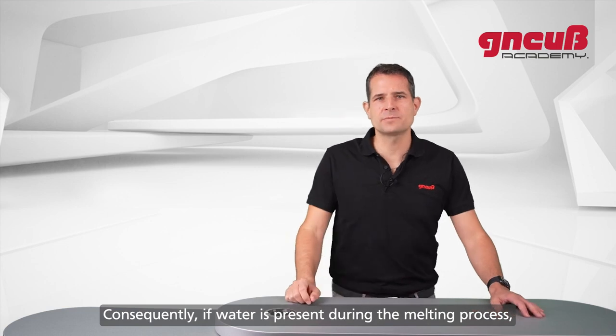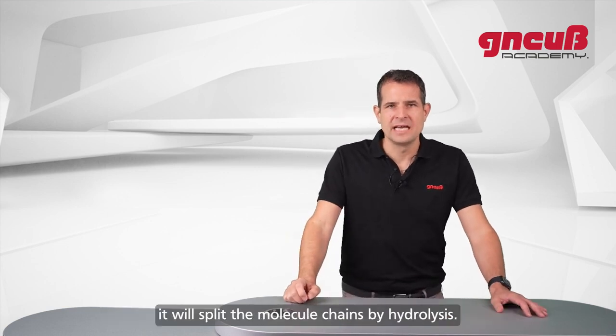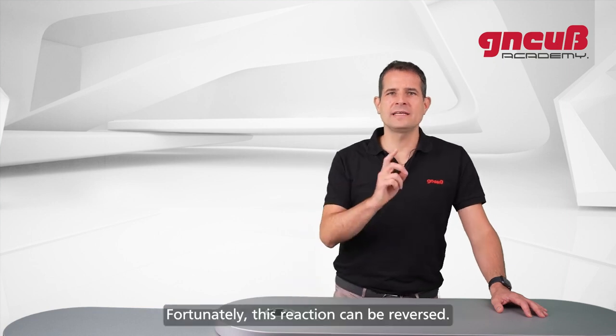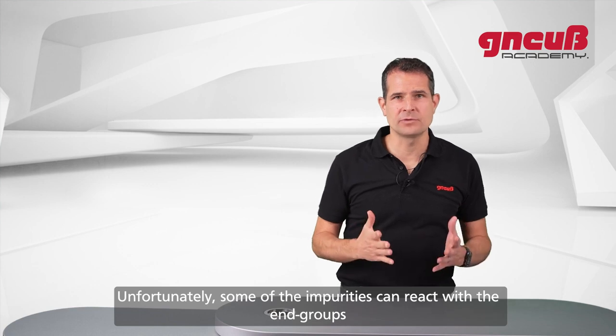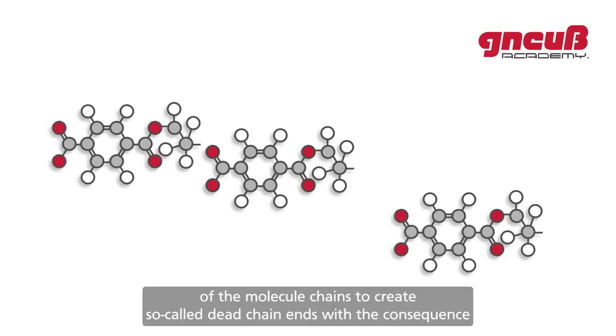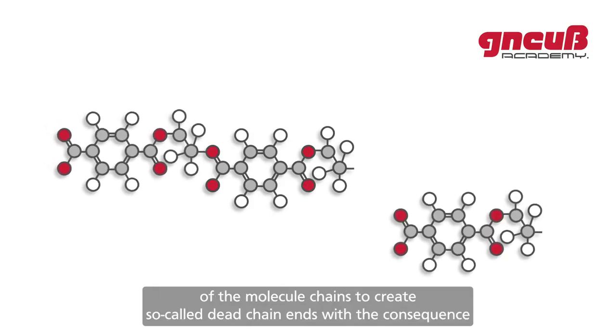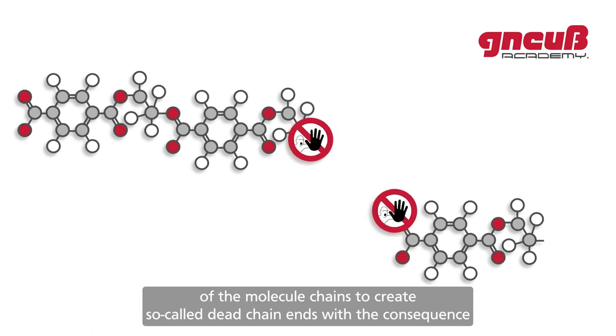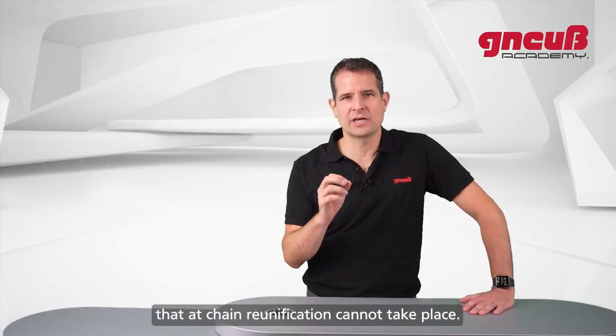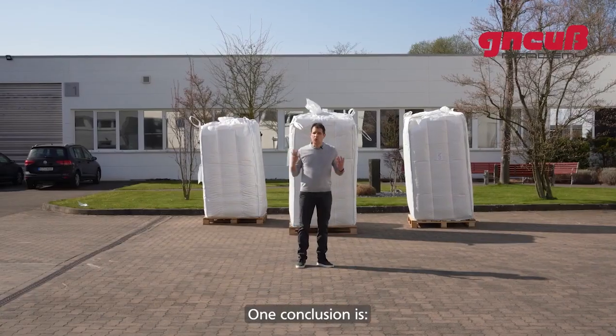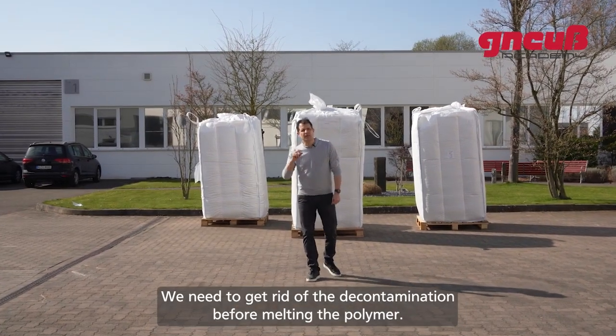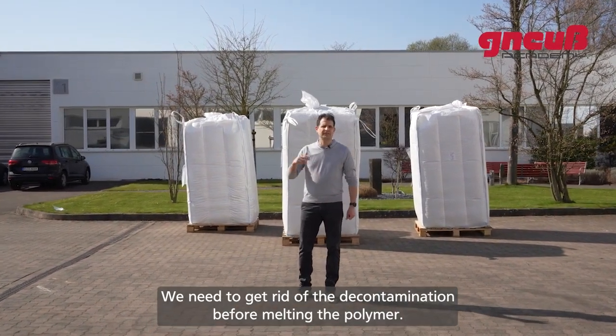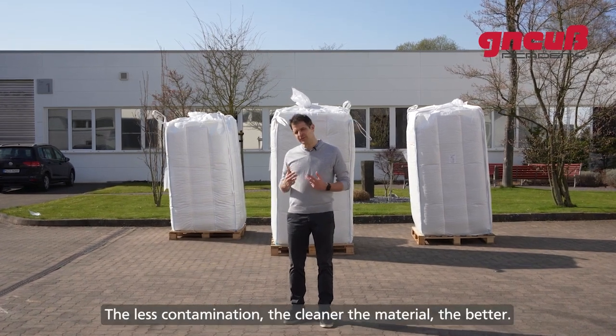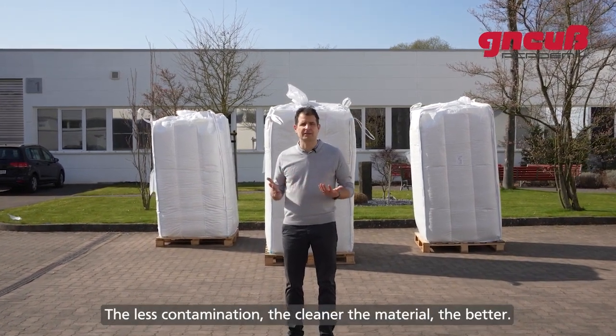Consequently, if water is present during the melting process, it will split the molecule chains by hydrolysis. Fortunately, this reaction can be reversed. Unfortunately, some of the impurities can react with the end groups of the molecule chains to create so-called dead chain ends, with the consequence that a chain reunification cannot take place. One conclusion is we need to get rid of the contamination before melting the polymer. The less contamination, the cleaner the material, the better.